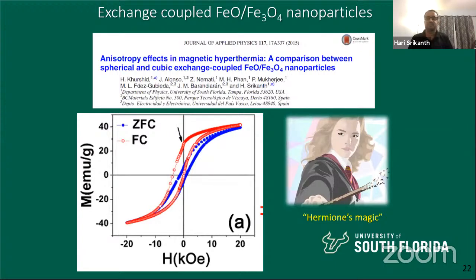You need some kind of wizardry that you need to exhibit in the lab to make very high quality nanoparticles. So we actually made these FeO, Fe3O4 nanoparticles. FeO is the core. And remember, the shell has to be biocompatible. So we have no choice there because the FDA will approve only biocompatible materials. So this is the Fe3O4 shell. So we've got the core shell particles.